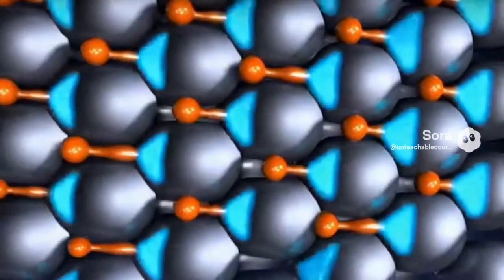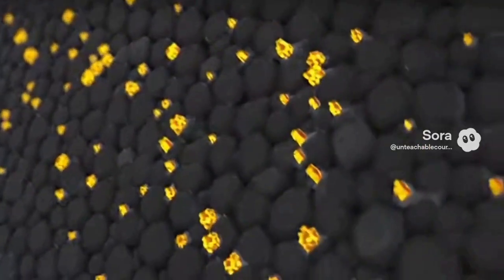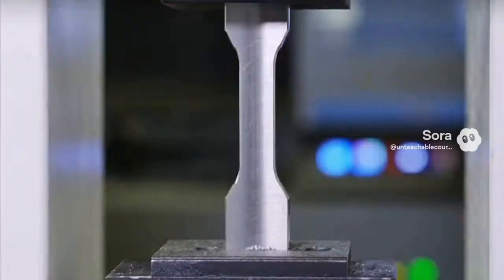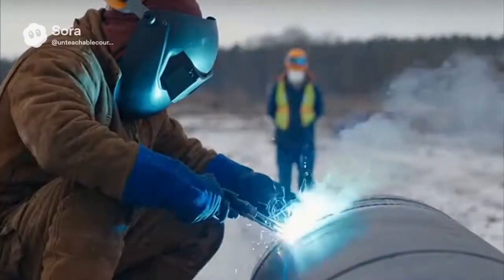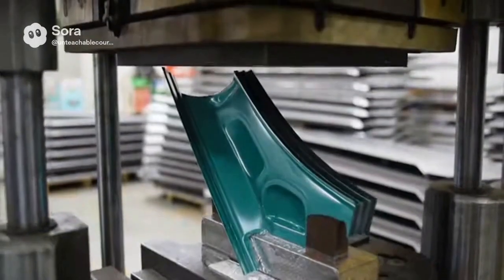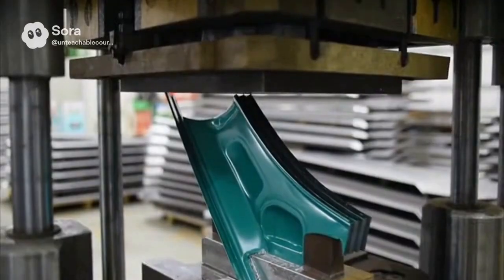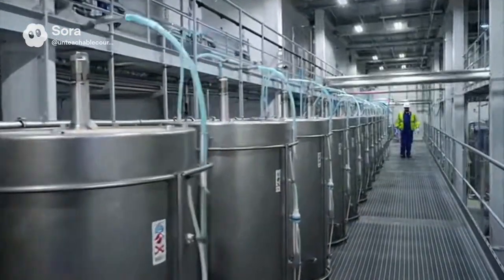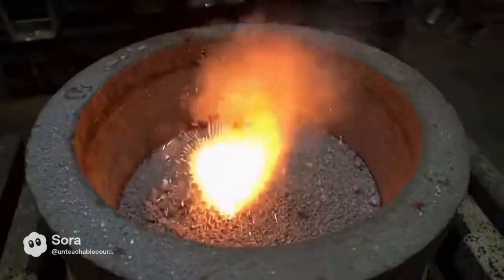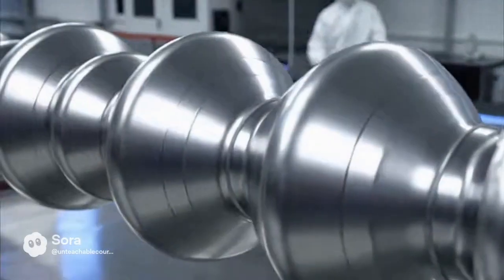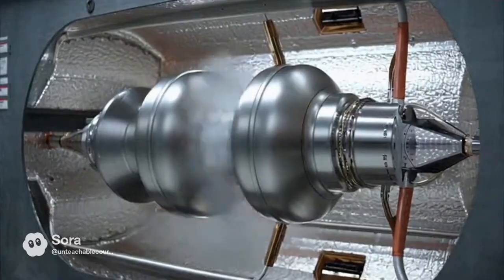Then, as the steel cools through critical transformations, niobium carbide and niobium nitride precipitate in a drizzle of nanoscale particles that pin dislocations and keep strength where you want it. If your coiling temperature is wrong by a few tens of degrees Celsius, you pay for it later. If your coiling temperature is right, the ferrite that forms is fine, tough, and obligingly strong without needing excess carbon.